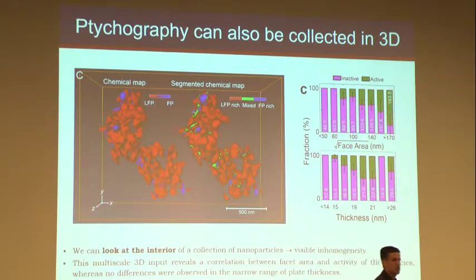Plotting the same thing, just different colors. What we noticed was not all particles are in the same states. If we represent the degree of delithiation of a given particle with the dimensions of that particle, there was a trend for the facet area to correlate with the degree of delithiation. The larger the particle, the more delithiated it was in these conditions, but not with the thickness. Arguably, the thickness variation was not very large. These are quite tailored particles. So that was the first thing that we were able to extract from this data.